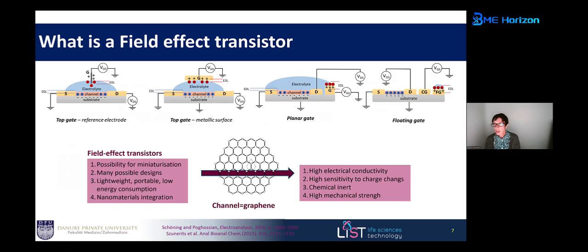In all these configurations, you can cover the channel, which is the sensing element, with graphene. And the reason we believe a graphene channel is extremely interesting for sensing is that graphene has very high electrical conductivity. It's very sensitive to charge changes, and it's very, very thin. That means all the charge changes you will see will go through this very thin film, and this gives it its very high sensitivity. On top of that, you have the chemical inertness of graphene and high mechanical stability. So all this together means you have a very sensitive and stable sensor at hand.